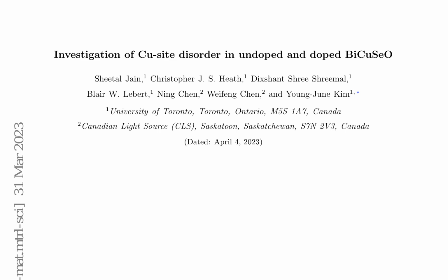EXAFS spectra in transmission geometry were also collected on these standard foils, along with each EXAFS measurement on the actual samples. To ensure suitable element concentration and uniformity, each sample was diluted with pure boron nitride powder, finely ground, pressed into a uniform pellet, and then affixed to polyimide tape.